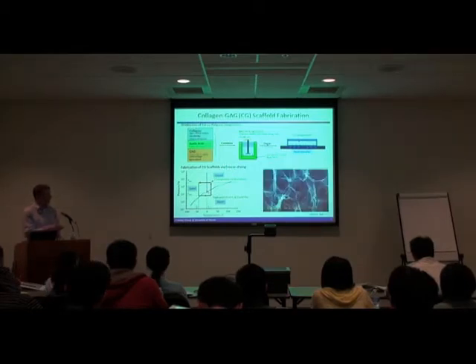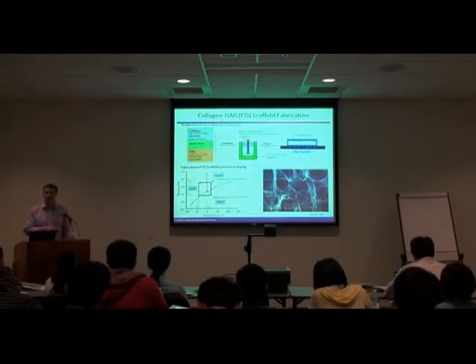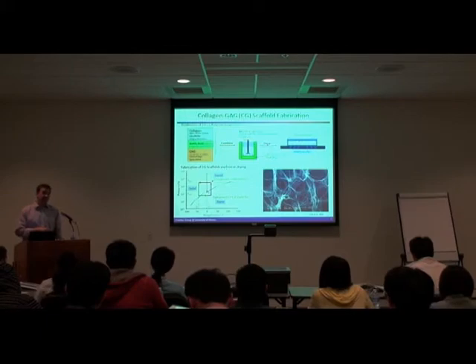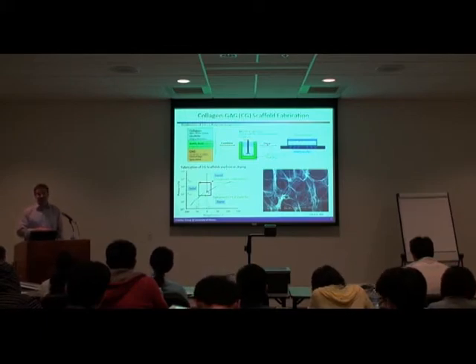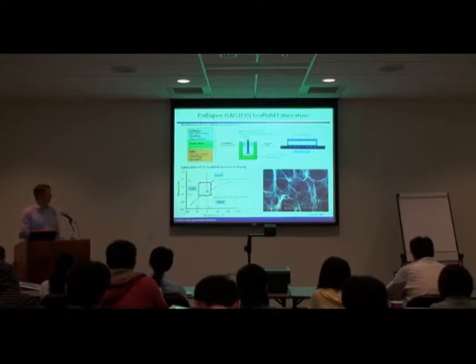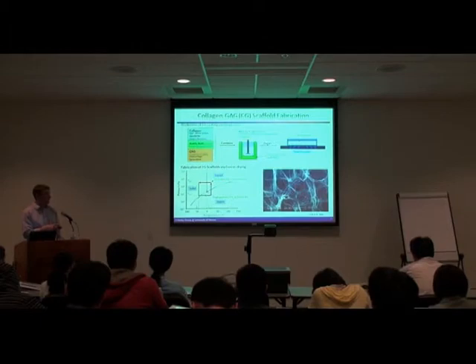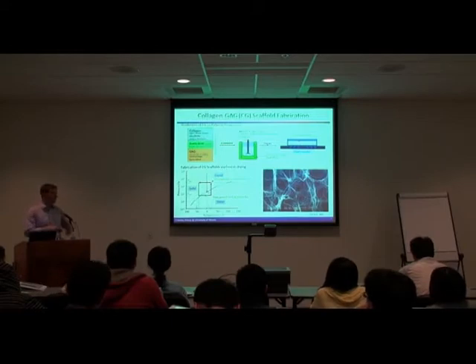What you end up with at the end is these nice low-density open cell foams. Most of these scaffolds are anywhere between 0.5 to 5% dense. That means their porosity is between 95 and 99.5% porous. So these are extraordinarily porous materials. What you're seeing here is an SEM image of one of our scaffolds, and the white content is the collagen-glycosaminoglycan structure, and the dark regions are pores. You're seeing many pores into the structure via this SEM image.